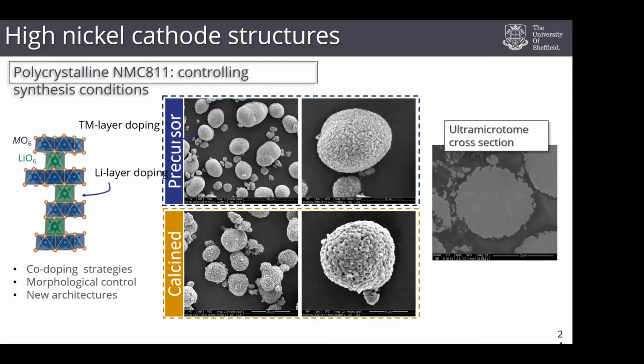So we've been making these sorts of new assemblies of our particles. We've learned a lot at Sheffield about how to control the synthesis so that we don't end up with any gaps in between particles, which can often happen. And you can imagine those gaps acting as sites for potential cracking to occur in these high nickel content cathodes. The other thing we're doing is, we're not just looking at morphology, we're also looking at the chemical structure of these materials. So sometimes, I've mentioned that lithium might not always go back into the position it should go into. Sometimes these metals swap places.